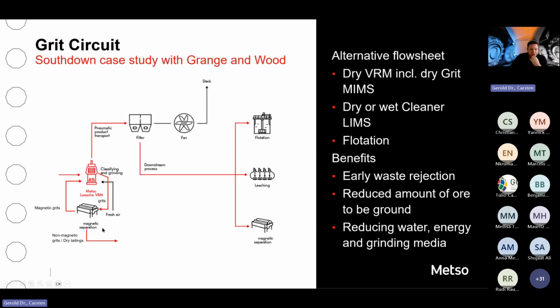of potential. And additional to just reducing the mass to be ground and optimizing the process, where it's getting really interesting, because this size fraction is about P80 250 to 550 micron. So you can do very nice things with that. Originally, within that project, all the gangue would have gone to a tailings pond. But within that project, because we could separate about 35% of this dry coarse fraction, that can be commingled with your fines from the other processes. So basically, just by changing the process, you suddenly can switch to dry stacking. And regarding the permit structure in a lot of ore projects, that's a real benefit.